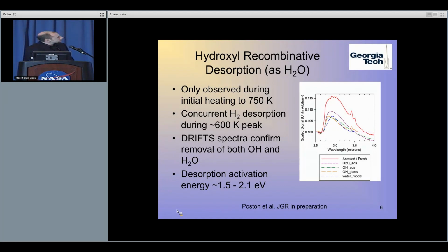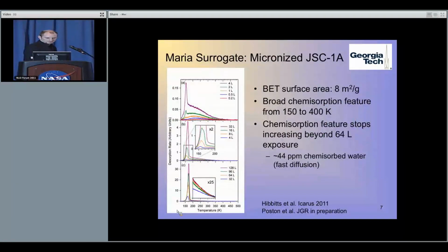There are these narrow peaks, and then there's a shape over here that is indicative to us of hydroxyls having desorbed. So we think we've confirmed that this peak at 600 Kelvin is hydroxyls recombinatively desorbing as water. The desorption activation energy for these is about 1.5 to 2.1 electron volts.